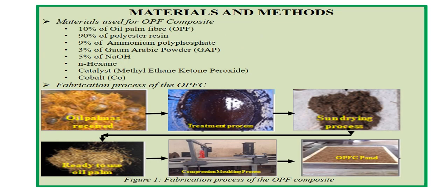The materials used for the oil palm fiber composites are as listed as seen. The fabrication process of the oil palm fiber composite began with first treating the oil palm fiber as received with n-Hexane to remove oil and impurities, and then wash with 5% sodium hydroxide to improve on the compatibility of the resin. It was then sun dried and was ready to use.